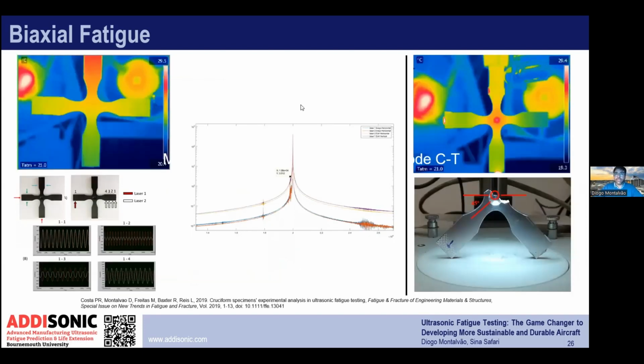There are obviously some problems, and here is a specimen that didn't work really well, and we had heating being generated at the top. We had some problems with the mode shapes, and here we have a spurious peak over there. So we need to make some adjustments to the design of the specimens because we want to have a pure harmonic signal.